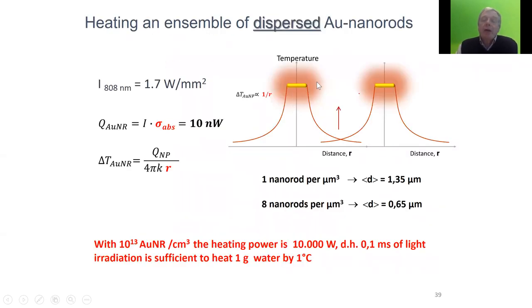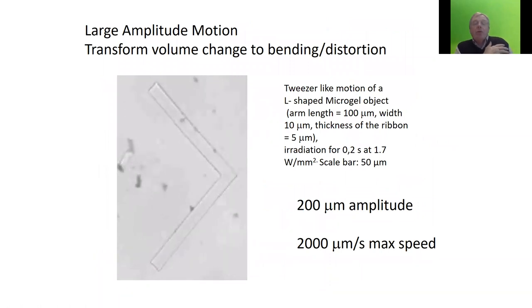Now, when you fill such a hydrogel with a few number of these rods that work as local heating elements, the distance between the rods can be relatively small. So if you have 1 to 3 rods per cubic micrometer, it's sufficient to heat up the material from inside the gel from inside very quickly and very efficiently in here. And that is what is shown here.